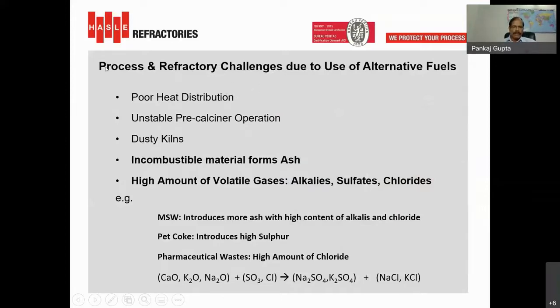On the process side, plants are facing poor heat distribution when using alternative fuels, sometimes unstable pre-calciner operation and dusty kilns. And also when these alternative fuels are burnt, they introduce more and more incombustible material in the system, in the form of ash. And when burnt, they release a lot of volatile gases in the system. These gases are especially alkalis, sulfates and chlorides.